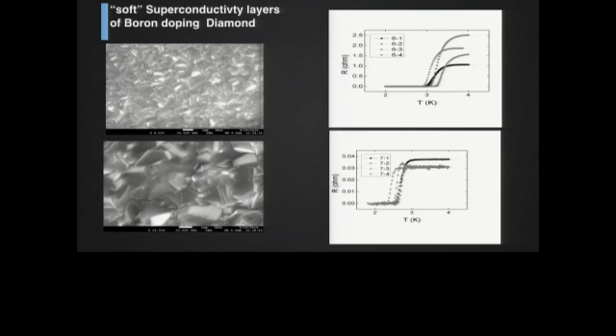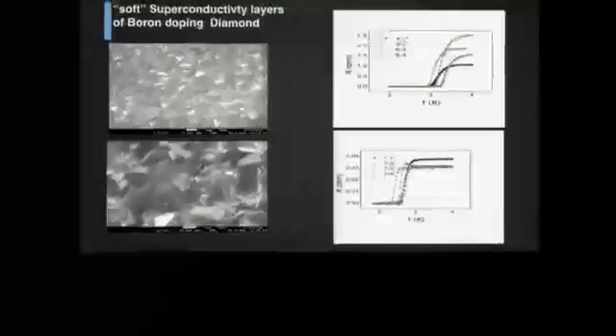And just to show you that we've been able to do that in some of our samples, this is the resistance here versus temperature. These transition temperatures are around 3 to 2.7, depending on where we are on the surface of the sample and the nature of the doping of the boron.